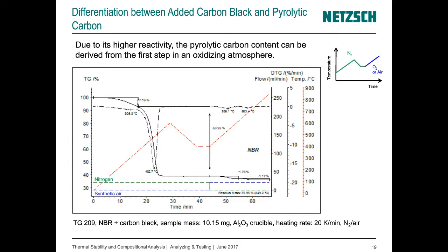If we use such a temperature profile, then the decomposition of the polymer, here it's NBR, does not take place completely. There's a certain amount of pyrolytic carbon formed. This pyrolytic carbon has smaller particles, a higher surface, and thus also a higher reactivity than the added carbon black, and therefore we can relate the first step to the content of the pyrolytic carbon and the second step to the content of the added carbon black.